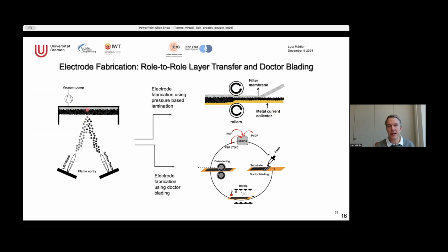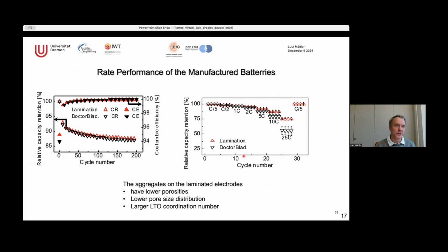And then we take this dry powder with the filter and, on a dry base, laminate this on the metal current collector. You could think about even roll-to-roll applications on this. And that really is a difference from all this calendering and doctor blading and drying and so on. And it's a one-step process. And if you make things right, these actually work quite nicely. As you see, for the same material, we did lamination and doctor blading. There's not so much difference.